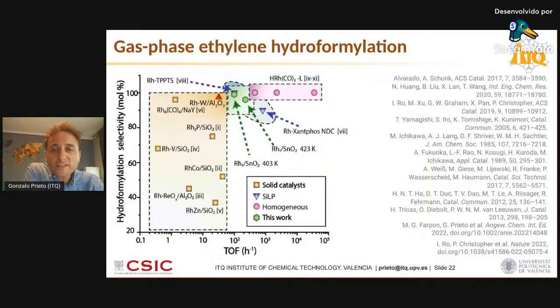The all solid catalysts that have been investigated to date, and those are the ones encaged in the yellow block, they show modest reaction rates, as you can see. And also, perhaps more remarkably, especially for those which are most active, so they are on the right-hand side of that yellow block, they show also limited selectivities to hydroformylation, typically below 70%, because they also trigger undesired olefin hydrogenation.